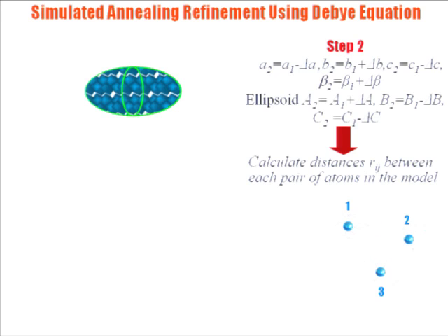What we did, actually, we replaced the point position for each atom with a, well, here an ellipsoid is shown, but we took a sphere in the first instance. And every time any of the atoms was involved in calculation of interatomic distances, this distance was chosen randomly within this predetermined sphere. And the sphere size, sphere diameter or radius, was also a variable parameter, one for titanium, one for oxygen.